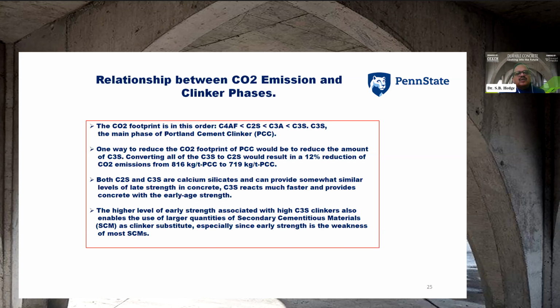So just to give an idea for the benefit of the attendees, I have mentioned the clinker phases: C4AF, C2S, C3S. The carbon emission level is getting reduced from C3S towards C4AF. That means, needless to say, that we need to have the C3S content at a moderate level, or you have to have a low clinker percentage in the cement. We will discuss this in the coming slides.